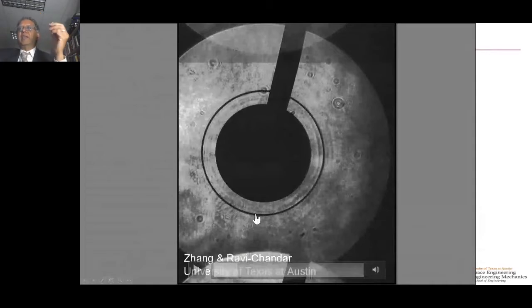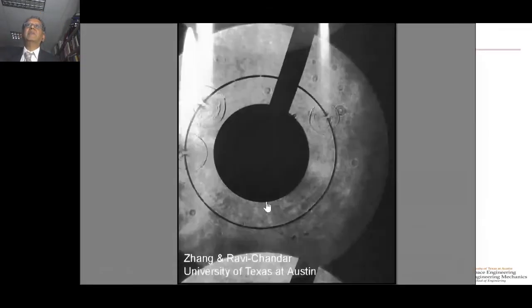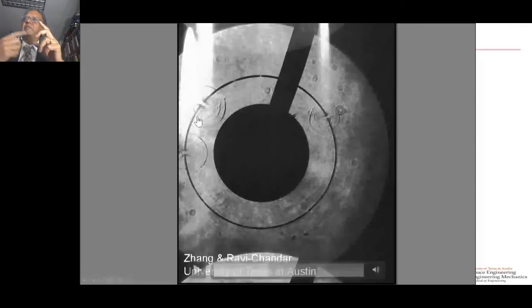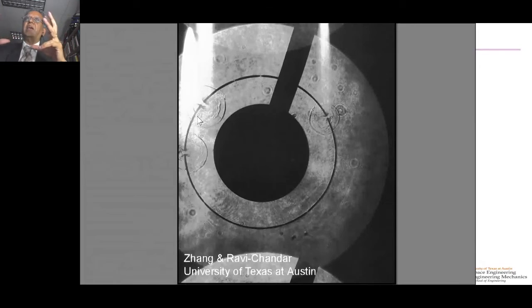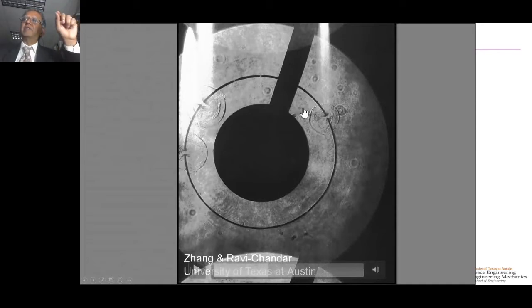But here's where Galileo's "measure what is measurable" comes into the picture. This particular camera has a combined streak mode and framing mode, so it is able to time resolve things in a particularly interesting way. More than that, when the ring breaks, it's circulating very high currents, on the order of tens of kiloamperes, so it is breaking a fuse. There's an arc that jumps across there. The arc creates a shock wave in air. The shock wave is visualized here through Schlieren images that are a part of the aperture of the camera.